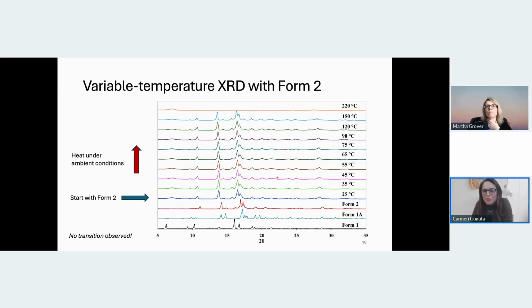Well, this is from my side: have you determined the crystal structure of these two forms? We have not. Okay. Because either from powder or from single crystals, you had a nice powder diffraction pattern, so it could be done. And if you determine the crystal structures, you can also see if there are voids in the structure, so enough volume for a little bit of water to get in. But I do agree with you that it has to be on the surface if you look at the XRPD. And one of the limitations in this study is that we had a limited amount of material from BMS. So I would be interested to have the full crystal structure, but it really was not accessible to us. You need to choose your battles.